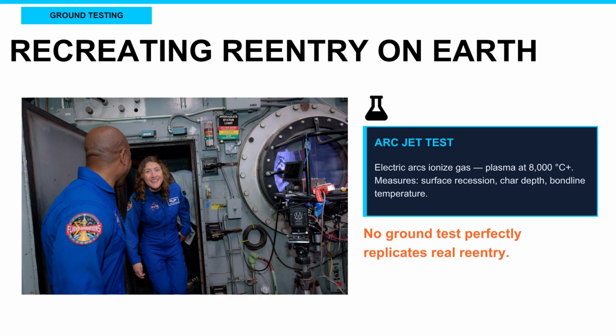Heat shield materials are tested on Earth before any flight. Arc jet facilities use electric arcs to ionize gas and produce plasma streams at temperatures and pressures that simulate re-entry. NASA Ames Interaction Heating Facility can sustain plasma at over 8,000 degrees Celsius. Test samples are mounted in the stream and monitored for surface recession, char depth, and bond line temperature.